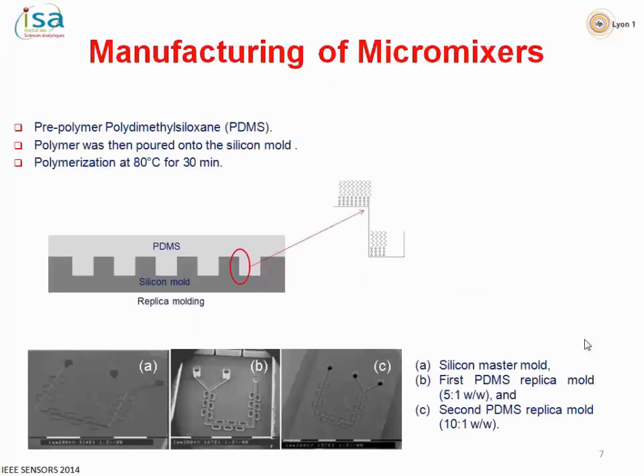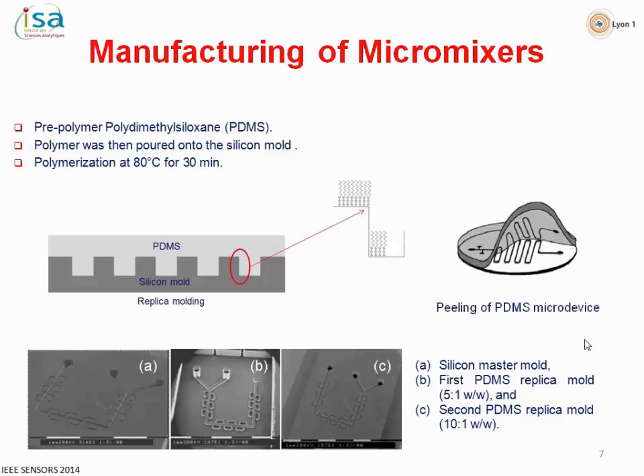Okay, after that we need to produce our master. Our master is based on polymers, PDMS in our case. For that, we need to use soft lithography. What does that mean? First of all, we have the silicon master that we need to functionalize previously, because after that we will put the PDMS on it and put it in the oven for 30 minutes, and we need to peel it off. Without this, we will damage our structures and it will not be useful, because we can have some leakage and so on.